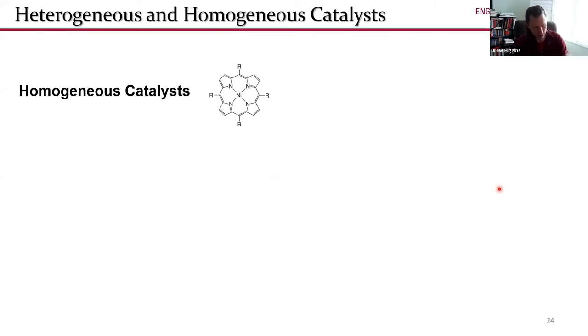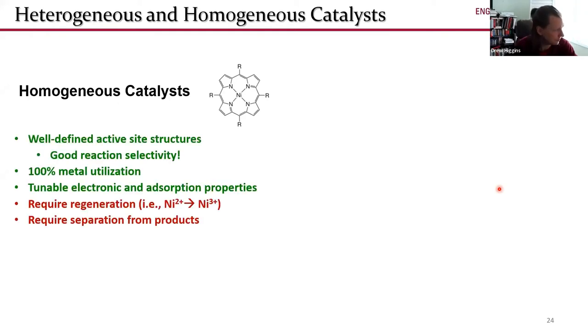So as I mentioned, these transition metal nitrogen carbon catalysts have an active site structure that is analogous to homogeneous or molecular catalysts. And that comes with a few advantages. For example, they can have very well-defined active site structures. And when you have a well-defined active site structure, generally your selectivity is fairly good because all of the active sites look the same or at least look similar and thereby favor the same product.